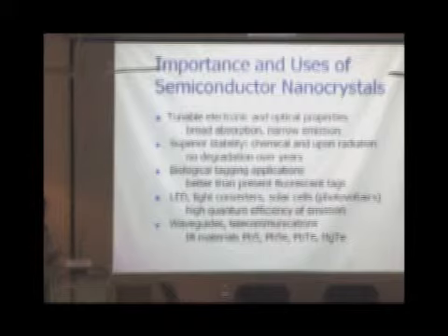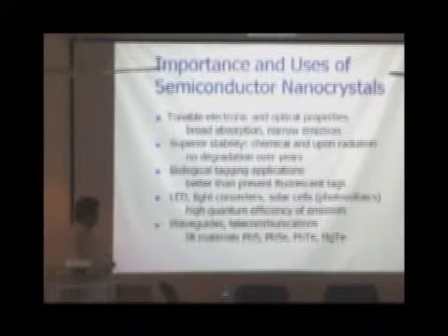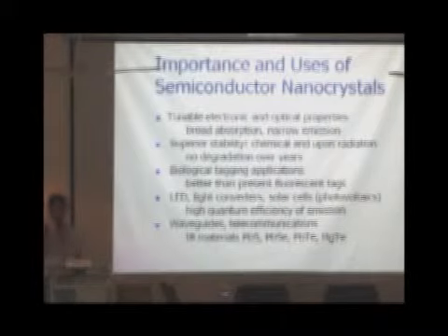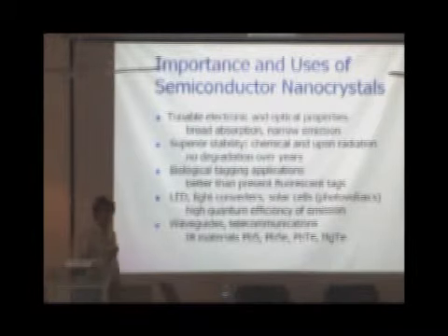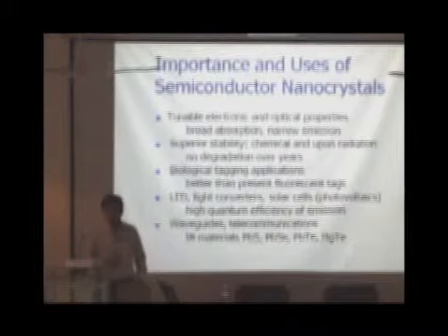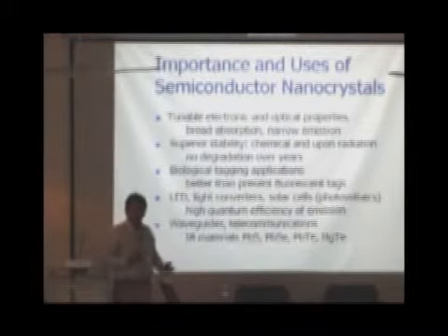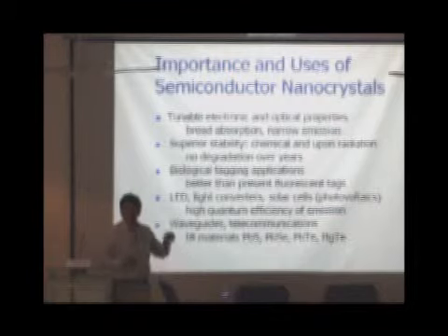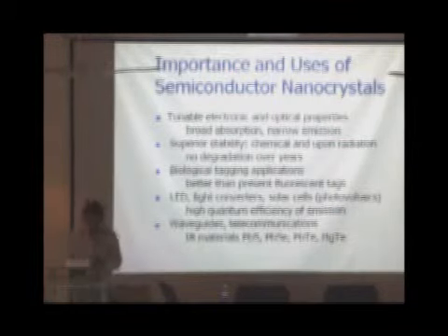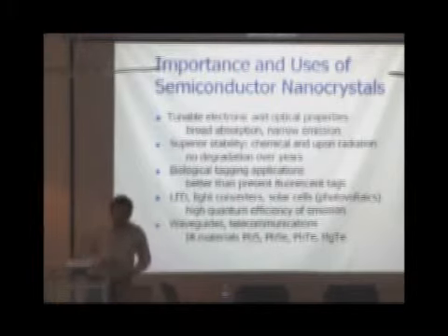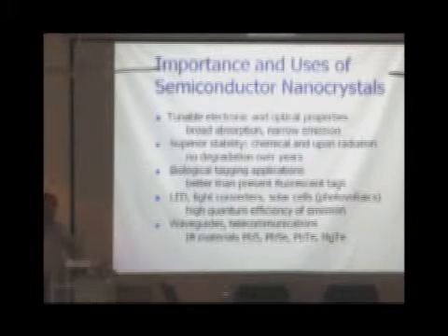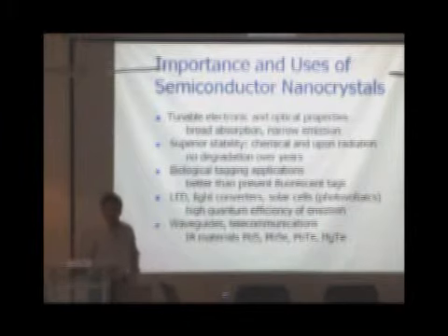These particles are very good. When people started research on semiconductor nanocrystals, these were not even stable for hours, but today we can make things that are stable for more than 3 years. They lie in the solution and still shine. The good thing is, compared to dyes which have been used for some of these applications, dyes degrade within 5 minutes of laser irradiation. So you have to reduce the power, which means you get more noise in your data. But nanocrystals don't degrade for weeks. You can continuously shine lasers on them.